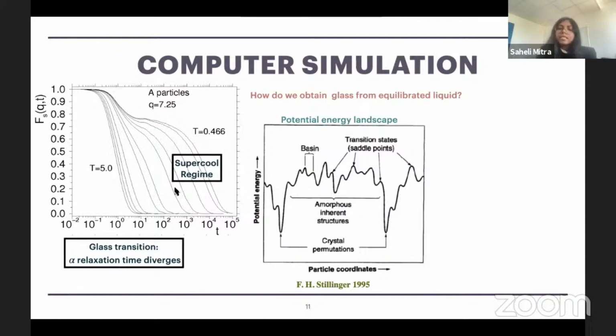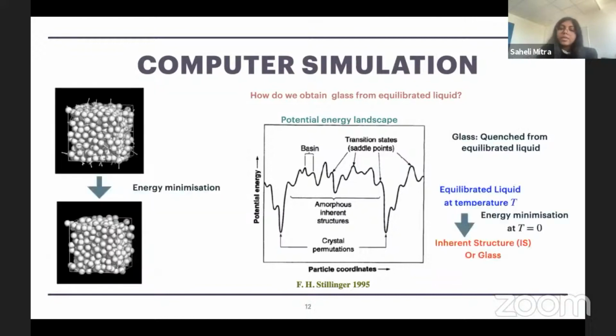So we can think that the evolution of the glassy material in liquid state is basically the diffusion through available inherent structures. To obtain a glass, we can start from an equilibrated liquid configuration, and then minimize the energy of the system so that the system gets stuck in one of these energy minimum inherent structure configurations. On the top left, I have a configuration in liquid state, and these little arrows show the direction of forces.